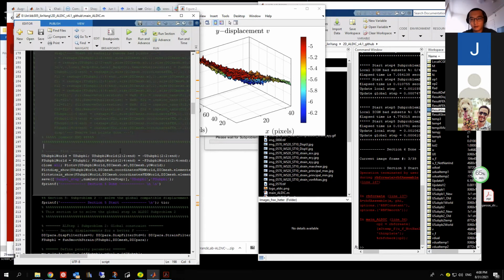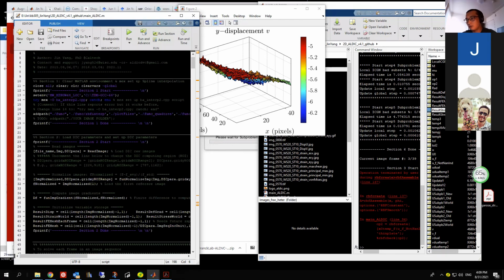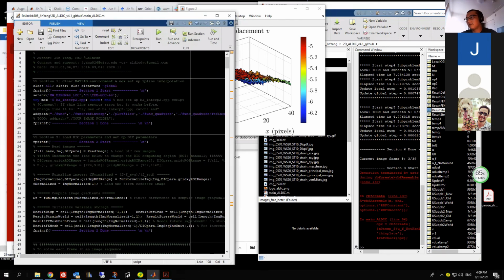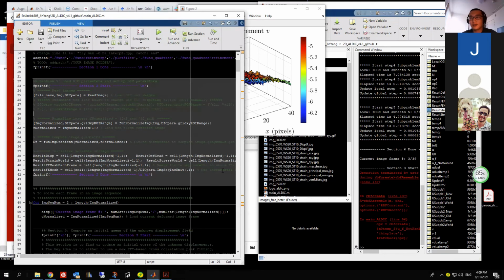Okay. Will there be a problem if you have large deformation? At least it can handle over 40 or 50 percent, it can handle very large deformations. And also if the deformation is super large, I coded the incremental method as well, but the accuracy is really doubtful. The most important reason is because for very large deformation, some regions will be out of the view. So you need to do lots of extrapolation. That's usually the accuracy is quite low.